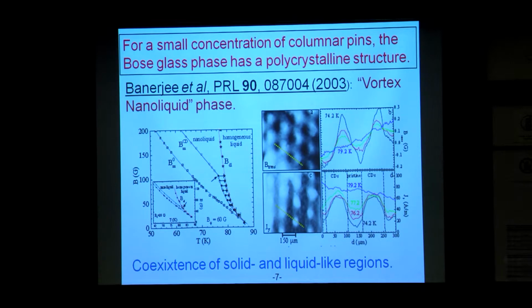Further experiments have shown that within this Bose glass phase, there is a region where one has something called vortex nanoliquid, which says that there is spatial inhomogeneity: there are regions where the vortex lines behave as if they're in a liquid state, surrounded by regions where the vortex lines look as if they are in a crystalline state. This vortex nanoliquid means that experimentally one has seen in this system coexistence of solid and liquid-like regions. Where this liquid-like region was coming from was not understood from these experiments as such, but then the modeling that we did told us that we have this polycrystalline state. The polycrystalline state has these grain boundaries, and near the grain boundaries you have liquid-like regions. One has some kind of melting near the grain boundaries.